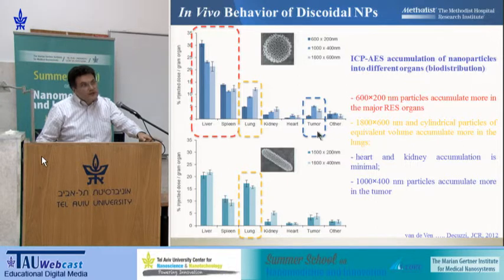I'm also presenting the data of the accumulation in the other organs because this is a biodistribution. And we got, of course, our good 20–25% of accumulation. This is normalized by the organ size. In the liver, we do have it, in the spleen, we do have it, in the lung, especially for the larger particles. But this is common to all nanoparticles. Sooner or later, of course, if they circulate longer, the particles will then end up in the reticuloendothelial system, no matter what. And so these particles have a circulation half-life which is very short, a couple of hours.